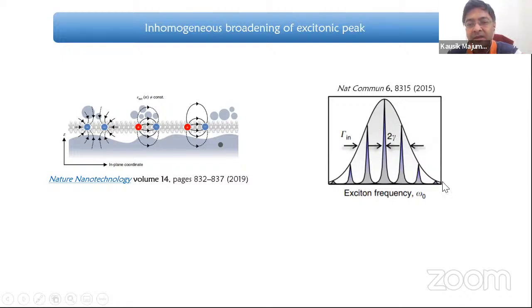On the other hand, if you come through a single phonon narrow resonance, then what you are doing really, let's say you're exciting somewhere here, and it resonates exactly with this. So nowhere else do these things come into the picture. So you're not relaxing to these states. You're only relaxing to this. And because of the singularity due to this resonance, only this state sees all the oscillator strength. And that's what we see.